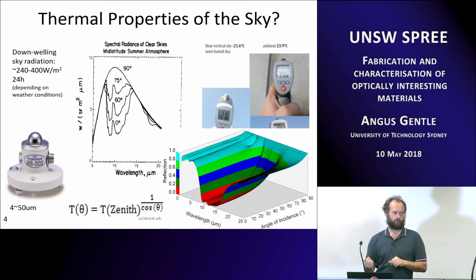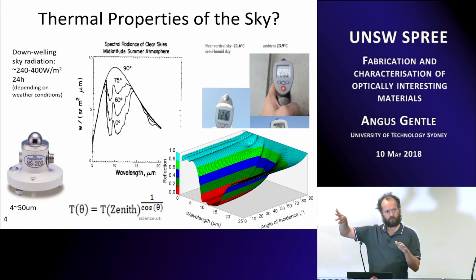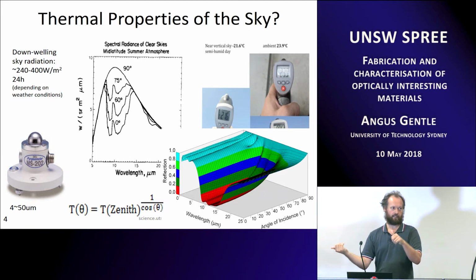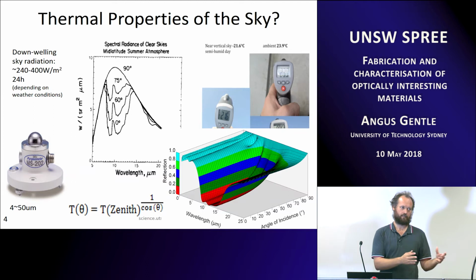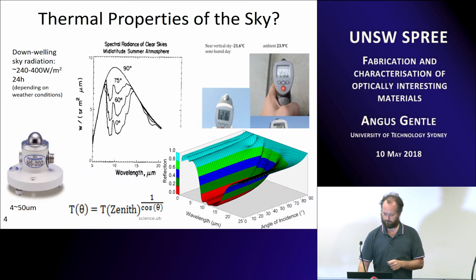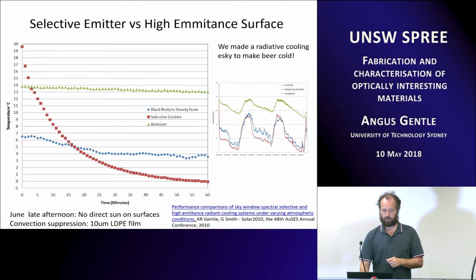we can design that with a thin film stack. This was 3 layers of silicon oxide, silicon carbide and silicon oxide, approximately 300 nanometers thick each. We're able to tune it so you get something that absorbs very strongly at exactly the same wavelengths where the sky window is transparent, but it also reflects at the high angles so you don't see the horizon. Making a thing like that, we can get very cold temperatures by just sitting a surface out in the sky, outside. So we put this sample outside.